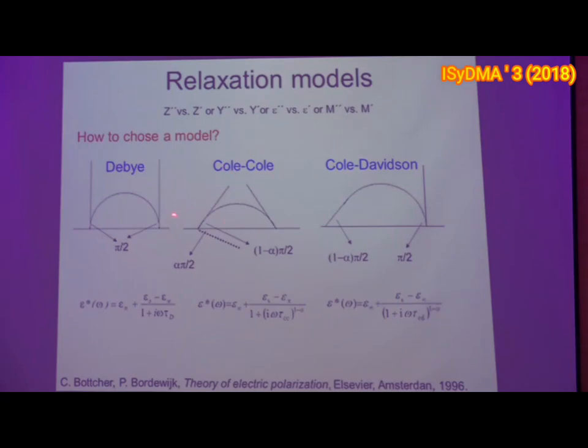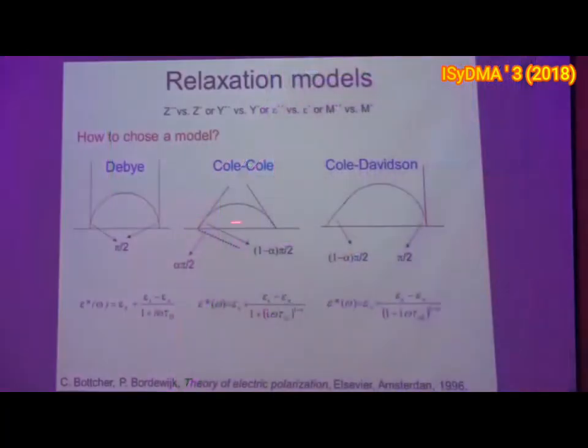So the Cole model, the difference is that this circle is not centered in the X; it is below the X, and we define this angle here. We call it the depressed angle, this alpha. When this alpha is 0, we are exactly in this Debye model. If the shape of this Nyquist plot is not symmetric, we can use this new function called Davidson that is not symmetric, and we also define these parameters.